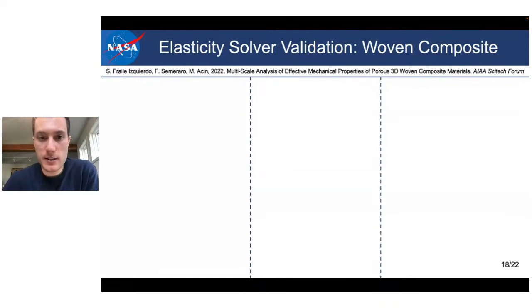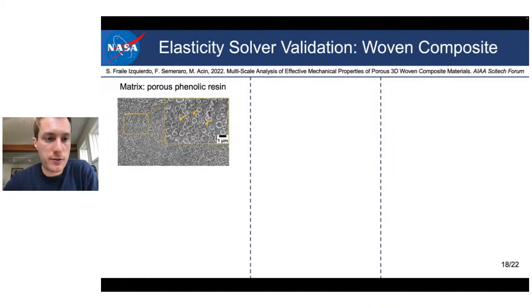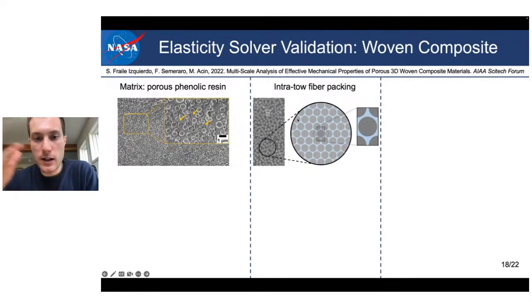On the elasticity solver instead, we decided to go a slightly different route, where we analyzed a woven composite at different scales, but each one of these scales is basically artificially generated. What I mean by that is, for example, this is again of very relevance to NASA. We have the porous phenolic resin that infuses the weave, and at the scale up, we considered the fiber packing, which is the interaction between this phenolic resin and the carbon fibers.